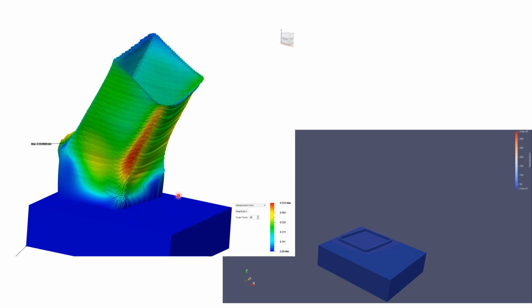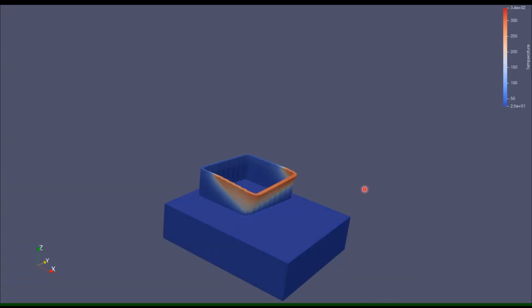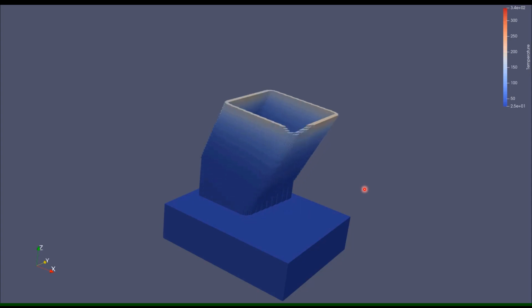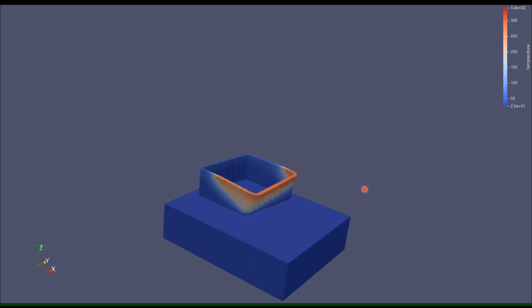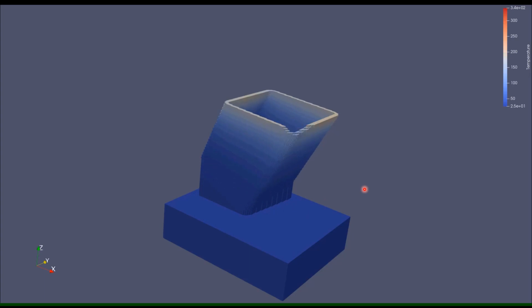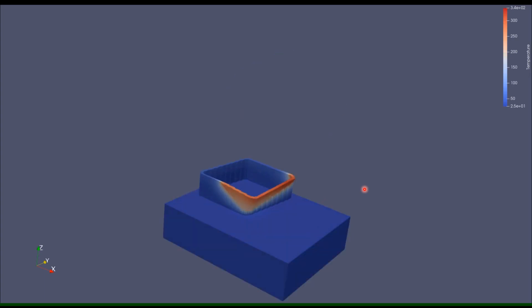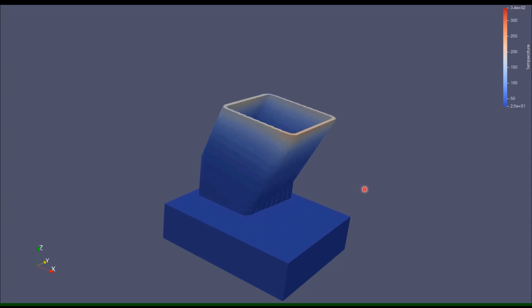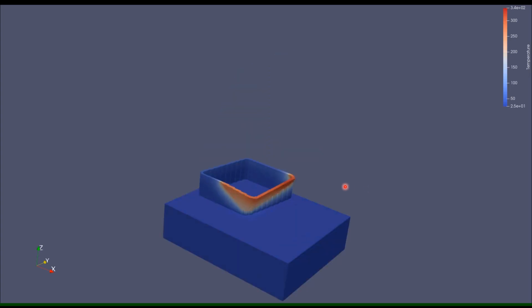So let's have a look at this temperature evolution over time, which can often tell us a lot about the root cause. What we can see here is that the tube, because it's been tipped over, the corner of the tube at the bottom becomes very hot earlier on because all of the heat has to flow through that small area, and that's really the root cause of the distortion. And if we want to fix the distortion, we probably need to orientate that tube normal to the build plate. So here we're using simulation to inform the root cause for the failure.